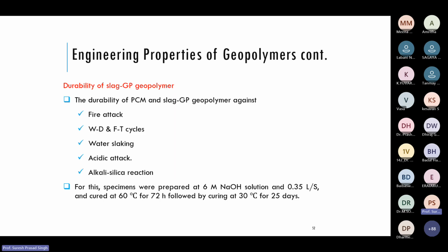So this is what I want to highlight. We studied the durability against fire attack, wetting-drying and freezing-thawing cycles, water slaking, acidic attack, alkali silica reaction, and all these things. All of these were done on specimens prepared at 6 molar sodium hydroxide concentration at a liquid to solid ratio of 0.35. Initial curing was at 60 degrees centigrade for 72 hours, and after that at 30 degrees for the rest 25 days. So total is 28 days curing. All these tests we have conducted.